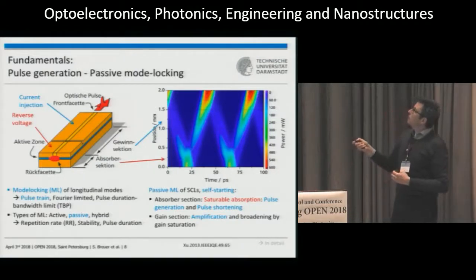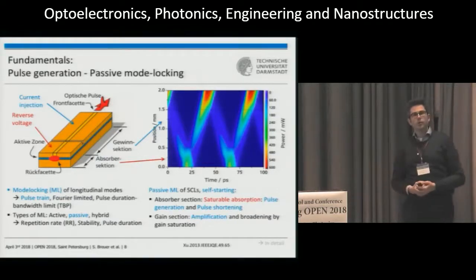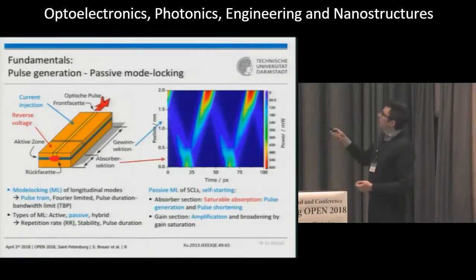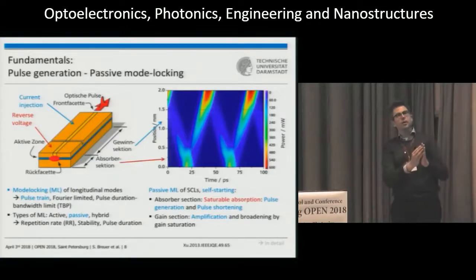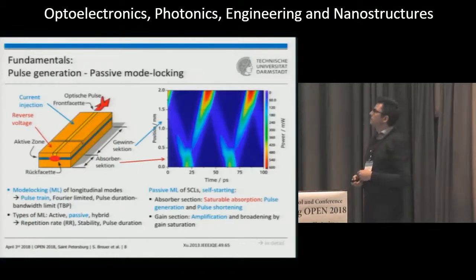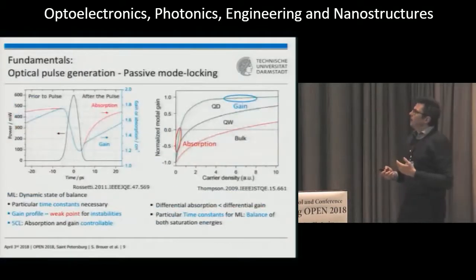So you can see here picture simulations by Team Turin. You have here the absorber section, the gain section, here's the output facet, here's the back facet. The pulse is reflected, increasing in intensity, then there's a pulse coming out, and back and forth and back and forth. So it's essentially saturable absorption process in the absorber that leads to the pulse shortening, and an increase in amplification that leads to the pulse peak power increase.